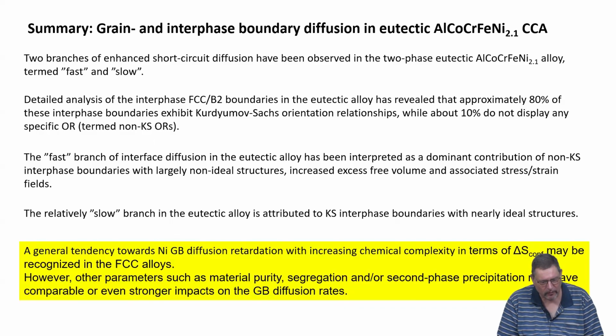So for grain and interphase boundary diffusion, I think it's important that the specifics of the structure of an interface between two different structures is as important as that of an interface called a grain boundary. For some grain boundaries with a very highly ordered structure, maybe a specific CSL type of boundary, diffusion will be much slower than in the volume. A typical example is the twin boundary. If it's a fully coherent twin boundary, you cannot really measure diffusion because it's so slow. But if it's a rather disordered structure, not any special orientation relationship, then these grain boundaries seem to feature much more enhanced diffusivity along the boundary plane.